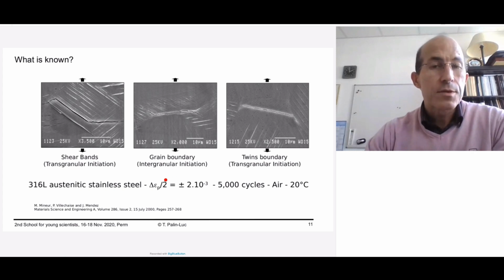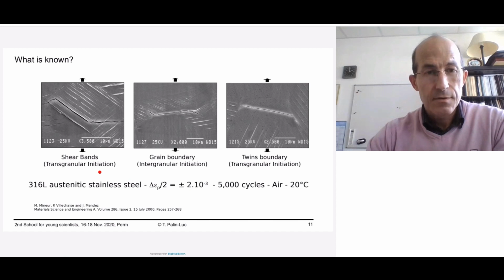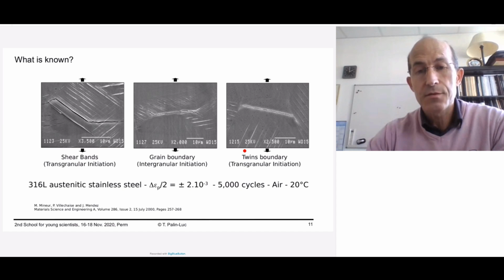So, what is known about the crack initiation phenomena? This is illustrated here. Three different features can be observed at the surface. First, the shear band or the slip band at the surface within the grain. So we talk about transgranular initiation. We can also observe crack initiation at the grain boundary, but close to the grain boundaries you can observe slip bands here. Finally, the incompatibility of deformations between two grains leads to the decohesion in between grains, and so the creation of an intergranular crack. It is also possible to observe within a single grain a transgranular initiation because of a twin. Because a twin is a defect in the symmetry of the grain or of the crystal.